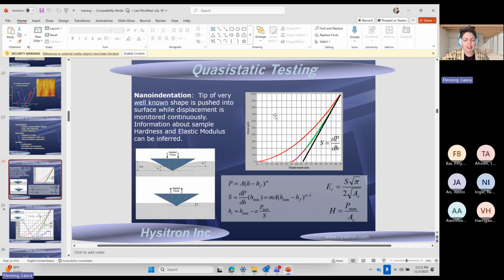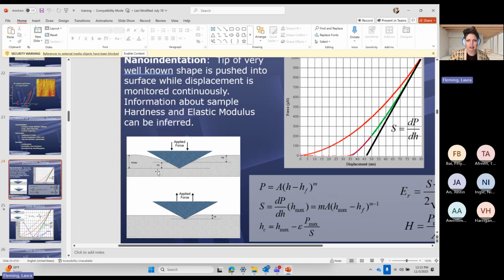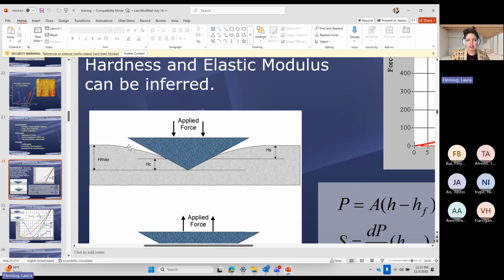So as that tip is pushed into that sample surface, you have some bending and deformation around the probe that's not actually in contact with the probe, which is what this is trying to show us here. So this is at the maximum force. We are indenting into the sample. You have this maximum depth, right? From the original 0 point of the sample surface, our max depth. Here's what our actual contact depth is. So you can see here that above this, the sample is not actually in contact with the probe. There is this contact area where all of the probe is in contact with the sample.